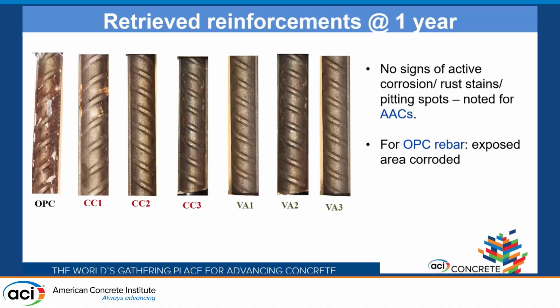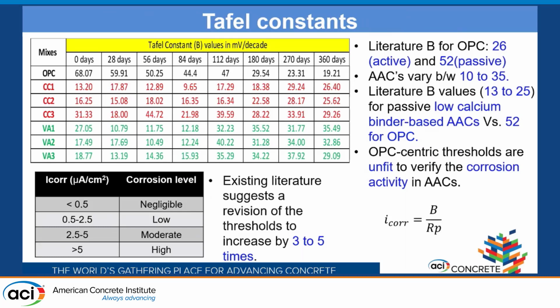This makes us revisit the basics. I-corr is obtained from B over RP. So there is something to do with the B. We have monitored this B over the course of our testing from 0 to 360 days. The AAC's B varies from 10 to 35 in passive condition, whereas literature reports B for OPC or Portland cement systems as 26 for an active corrosion system and 52 for a passive system. Our values of 10 to 35 are close to all the values reported for these low calcium based binders, which have been reviewed till now for AACs, against 52 for OPC. Hence, these OPC-centric limits certainly won't work to predict corrosion activity in alkali-activated concrete.